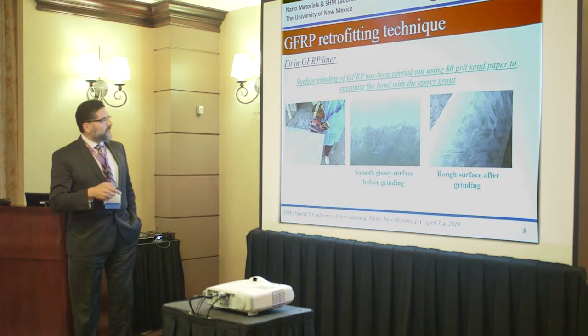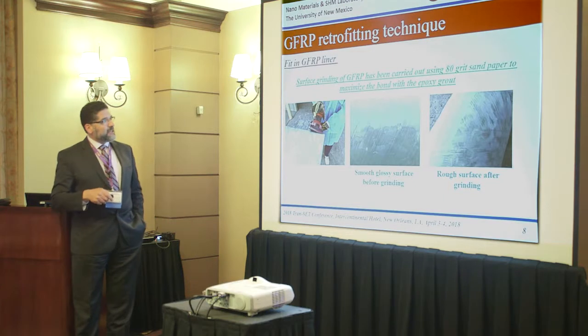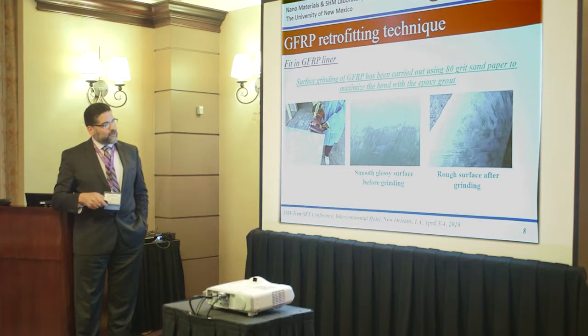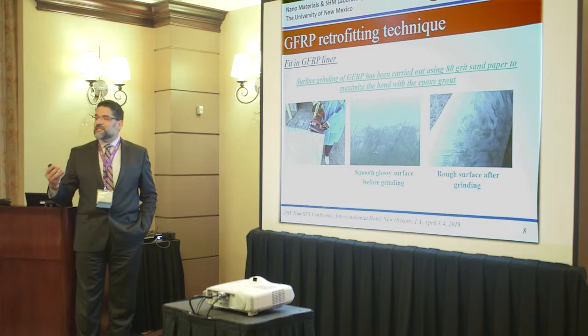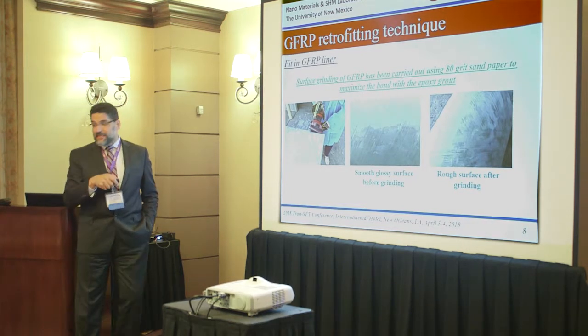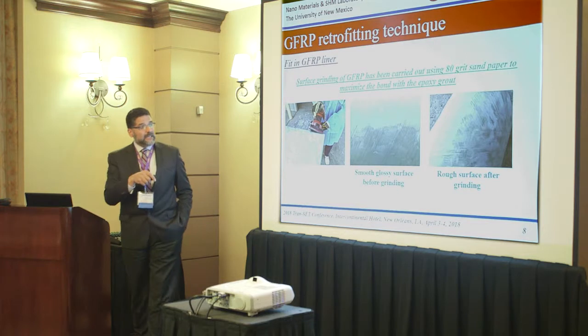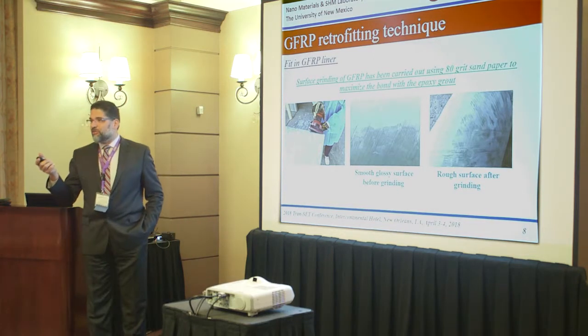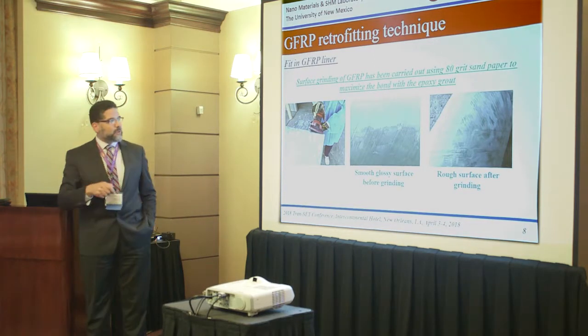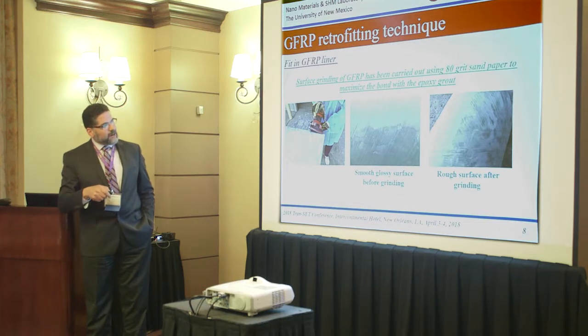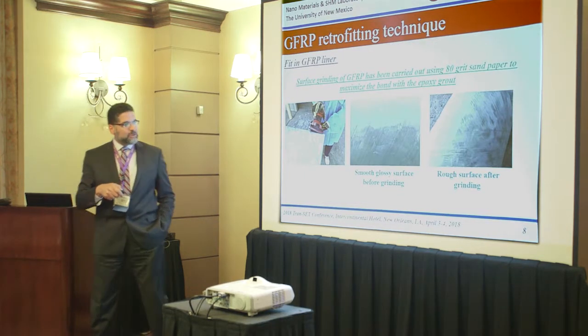To start the work, we need to do some surface grinding of the profile of the pipe or the GFRP section. Again, if this is being produced for that project, that step might not be necessary. But this is again just a glass fiber profile produced for any other use as well. So we have to roughen the surface to make sure there is a good bond.